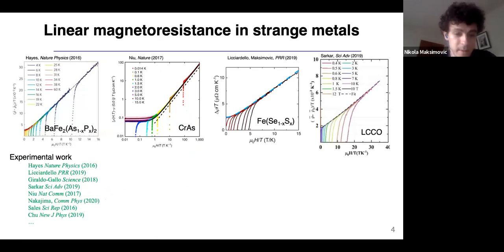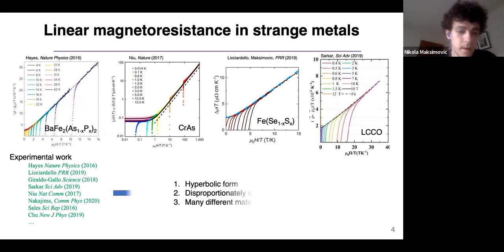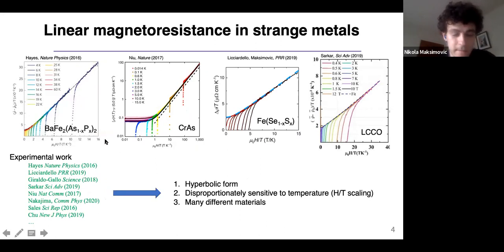So there have been several experimental papers on this topic. I would say this started in 2016 with Ian Hayes's paper on phosphorus-doped barium-122. But since then, many quantum critical systems have shown qualitatively similar behavior. And there are three main things that we can take away from the existing data. One is that the magnetoresistance generally has a hyperbolic shape, meaning it's B squared at very low fields, but then there's an extended range of linear in field resistivity.